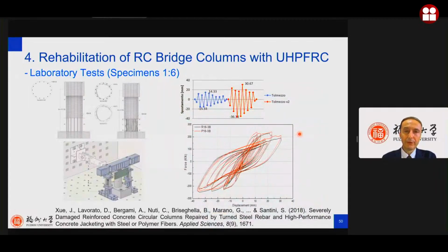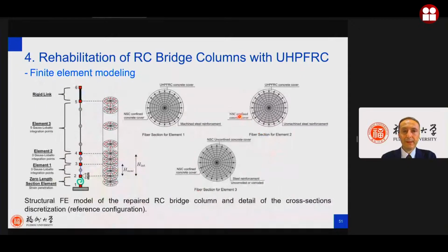And of course, we tested it. We saw tests 1 to 6, but I told you we also did tests 1 to 3 in our lab in Fuzhou, using this setup and applying a displacement history that was taken from an earthquake in Italy in 1976. And we also implemented finite element models. As I told you before, I already showed you these models where we consider all the different effects we have, with the strain penetration and so on.